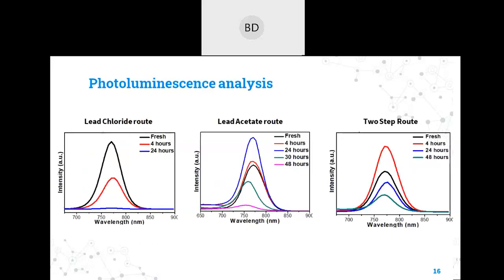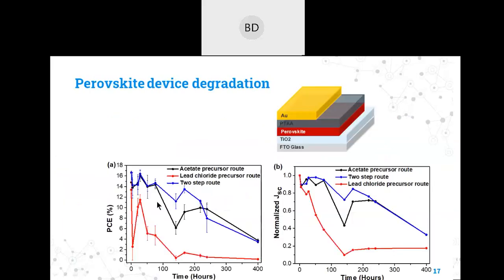To have better confidence in this observation, we did the luminescence studies as well. If you see, even after 24 hours, the lead chloride film is not at all photoactive. But in the case of lead acetate and two-step routes, it shows photoactivity even after 2 to 3 days or 4 days also. So clearly, the lead chloride route was degrading faster.